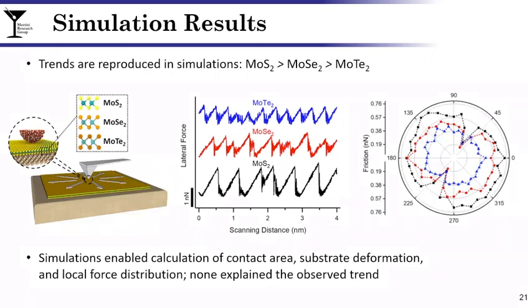We repeated the simulations in different scanning directions and found that sliding in any direction except the one low friction direction, we see the same trend of MoTe2 being lowest and MoS2 being highest in terms of friction. In the one very low friction direction, the friction was so low that we really couldn't differentiate it. We analyzed all sorts of different possible explanations for this: contact size, substrate deformation, force distributions on atoms. None of them really explain this somewhat surprising trend.